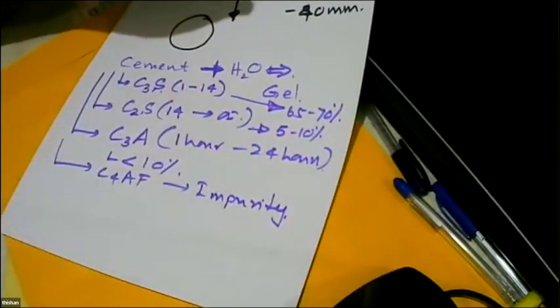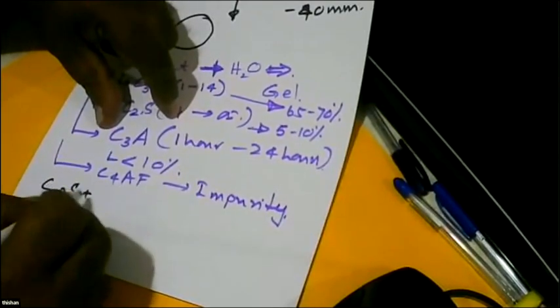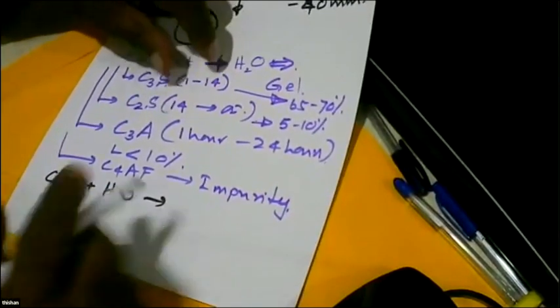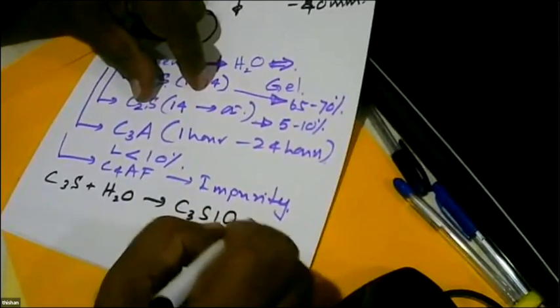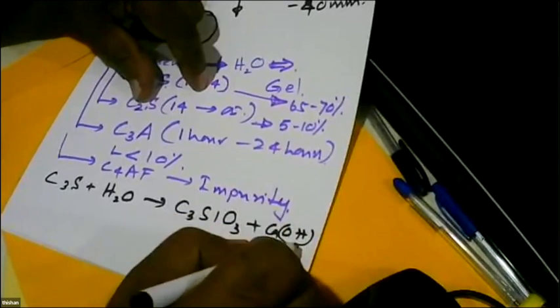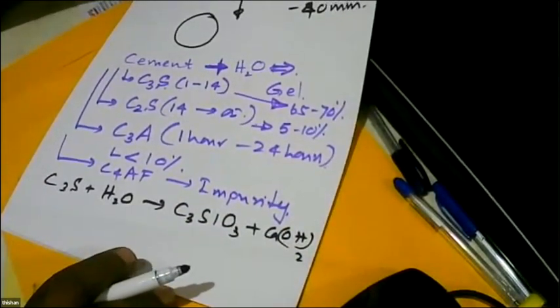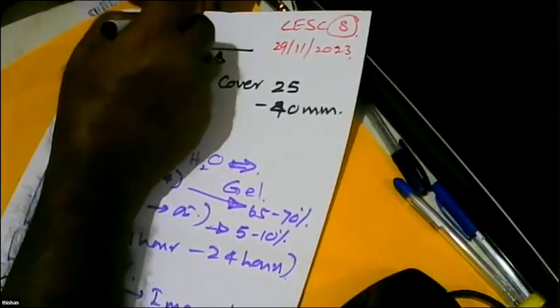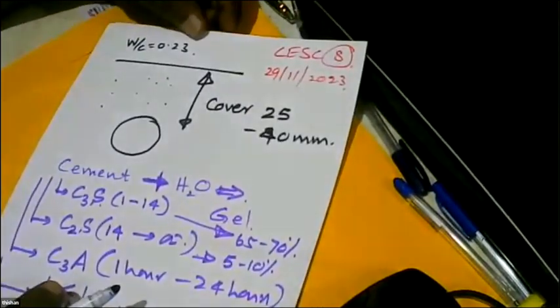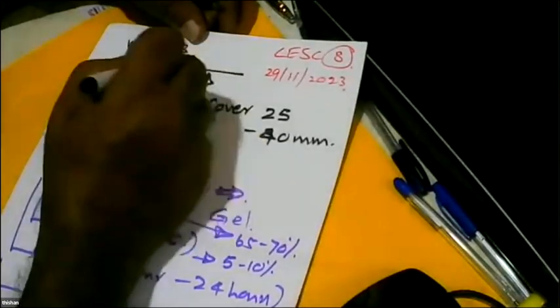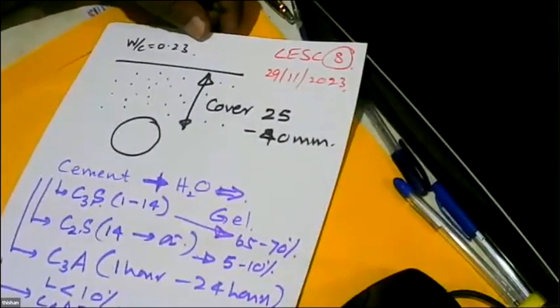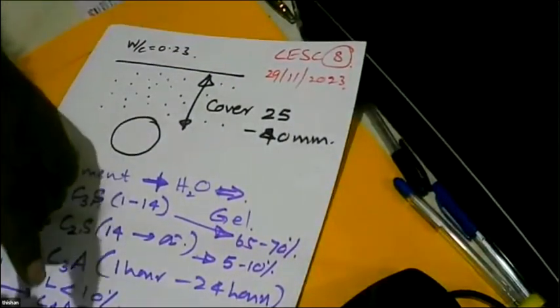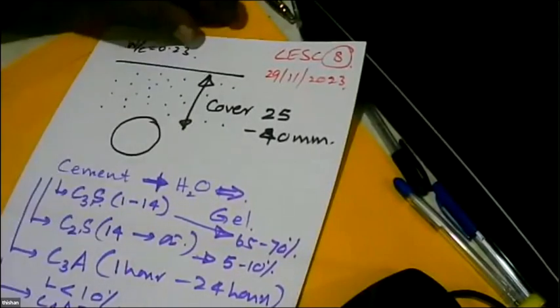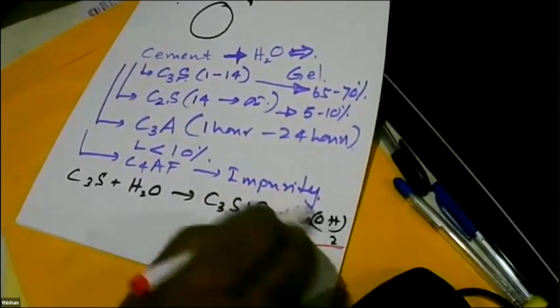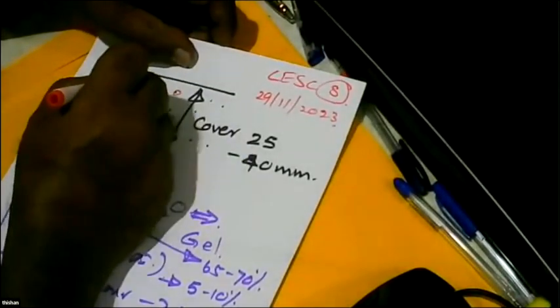So what is the reaction? Tricalcium silicate reacts, and dicalcium silicate also gives the same reaction, but at a very low rate. You get calcium silicate gel plus calcium hydroxide. Now, this calcium hydroxide is a very important ingredient because when you use concrete, what is the minimum water cement ratio needed? 0.2. What are we using? We use 0.5. So what will happen? All this extra water will evaporate. Then what do you get? Porous concrete. So what happens when you continue to cure? We continue to generate calcium hydroxide, and all that calcium hydroxide will start filling up these voids.